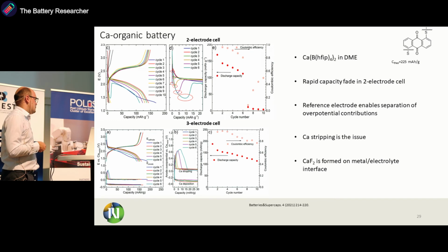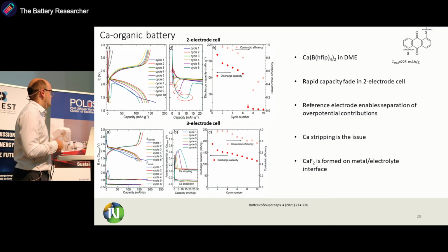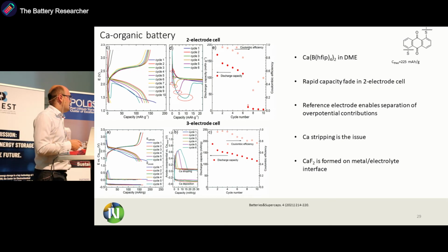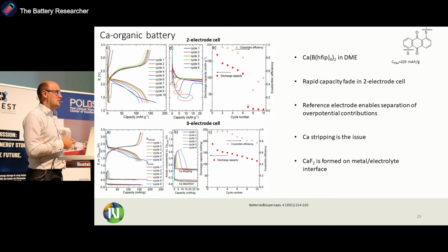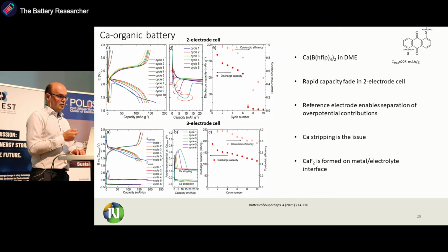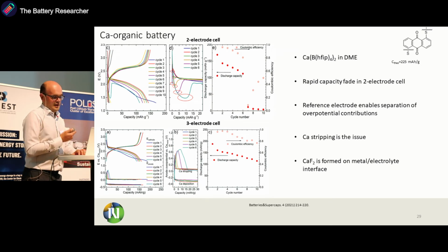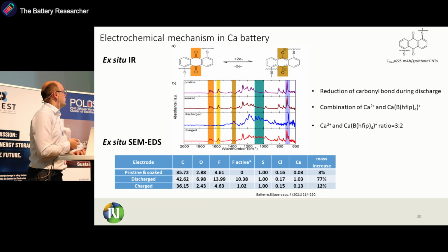But on the calcium metal anode, there is basically this bump, which is originating here. It's at the start of calcium stripping. So most likely this is attributed to decomposition of the electrolyte on the calcium metal electrolyte interface. And according to the literature, it can most likely be attributed to calcium fluoride forming there. So it means that basically the calcium electrolytes are still far from perfect, although they enable us to do cycling of our batteries for quite some cycles with good performance.